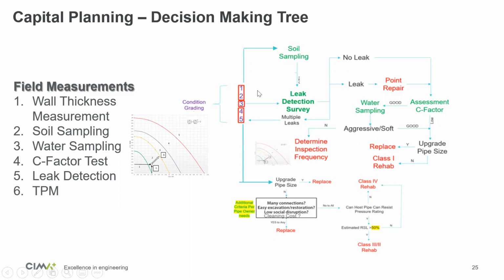So if the pipe gets a condition grading of 1 or 2, which means that the pipe is in good and fair condition, we always recommend additional soil sampling to see if we have overly aggressive soils. And if we have more aggressive soils, then it will be recommended to do more frequent inspections in order to keep an eye on that pipe. If we get the condition grading of 3 or 2 to 3, then we recommend to do leak detection.